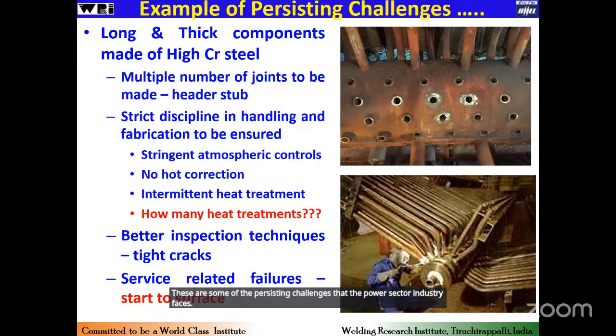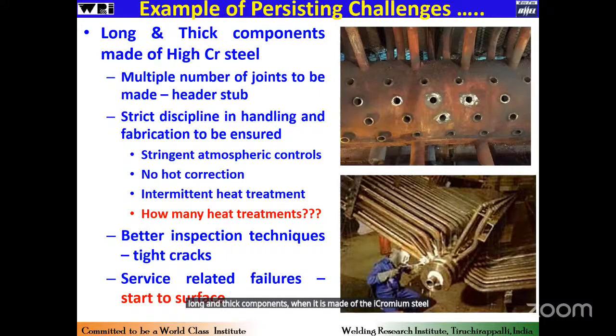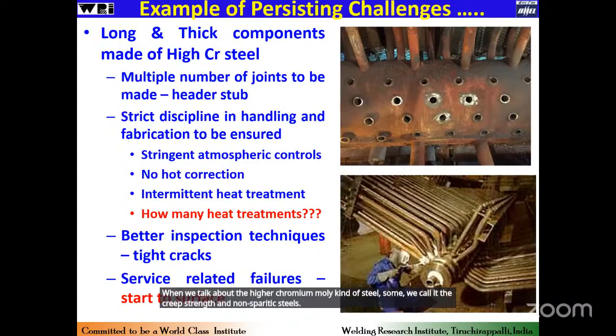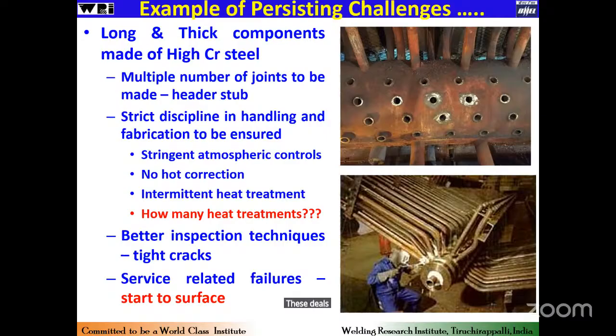Long and thick components, when made of the high chromium steel, will have multiple joints to be made, especially for the header stub kind of applications. When we talk about the higher chromium moly kind of steels, we call them the creep strength enhanced ferritic steels. These steels will necessitate the use of strict discipline, especially in handling and fabrication. So the atmospheric control has to be very stringent. It will not tolerate what carbon steel does.